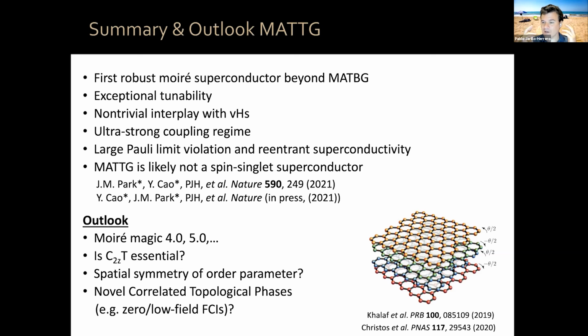one of the favorite candidates by theorists, an intervalley coherent state, okay? Where you have two of these Chern bands occupied, for example, depending on whether you're at +2 or -2, and the other two unoccupied, okay? And it's an intervalley coherent state, so it's a spin polarized state. You can have spin valley polarized states. You can have valley polarized states without spin polarization. You can have many very different many-body ground states depending on the filling factor and the model, okay, and the conditions of this system.